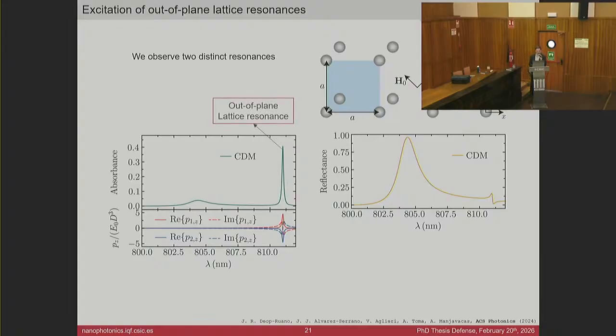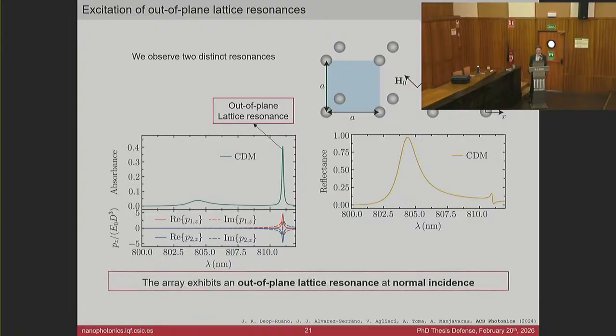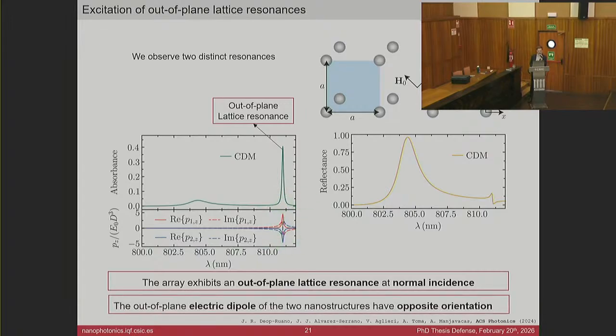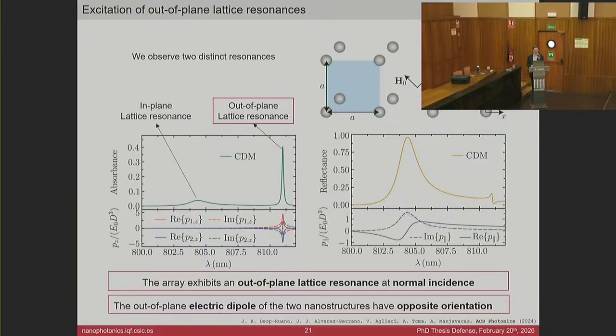So this is actually an out-of-plane lattice resonance. And something interesting is that we can observe that the two nanostructures are in antiphase. The two out-of-plane dipoles are in opposite directions. Now, for completeness, I'm also going to show that the other resonance is a more conventional in-plane resonance. And I also show you here the results of a finite element method simulation, showing that there is a really good match with our model.